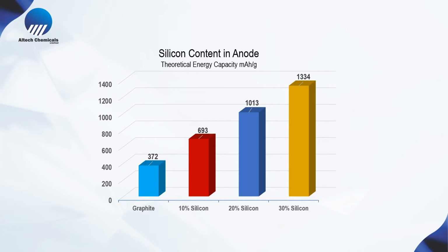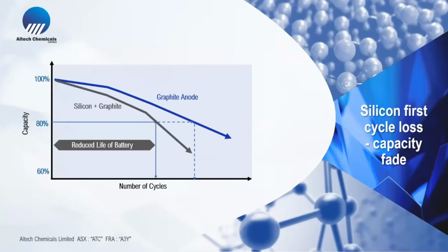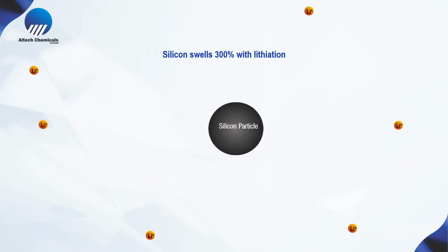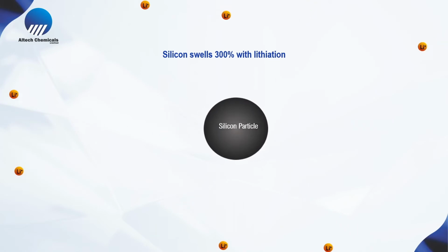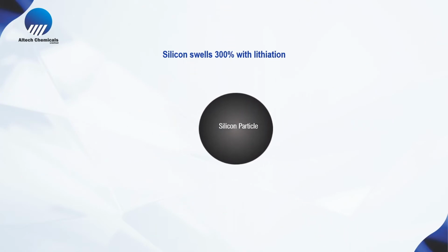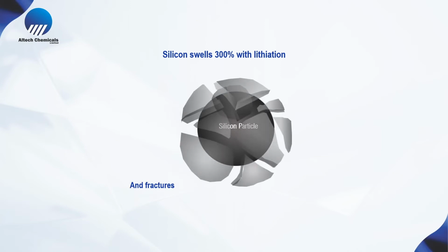And you can see the potential by adding silicon in the battery. I mentioned this fast fade. This is what happens with silicon if you don't resolve the three problems. It actually is detrimental to the battery. So what we have is this fracturing of the silicon particle on lithiation. And also, when it does fracture, it has delamination on the anode side. And this is a big problem for batteries.